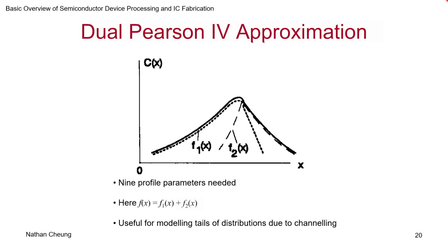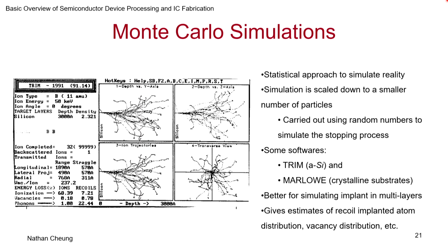But then the difficulty is sometimes you need more accuracy. So let us see what further. They actually use Monte Carlo simulation. Again the question is how many ions will you model in the implantation. The actual number of ions that are coming is 10 to the power 14 per centimeter square. If you do that number of simulations, it will take several years or centuries, or even more, if you want to do it accurately. You actually do only some 1,000 ions, or maybe 10,000, depending on computer power, but it's far less than the actual number of ions.